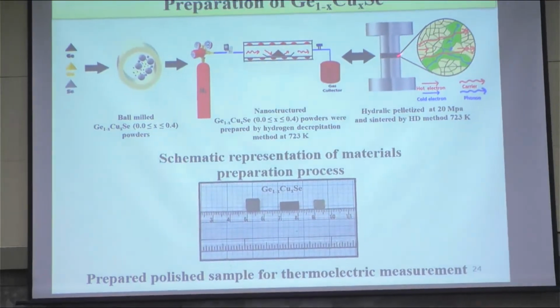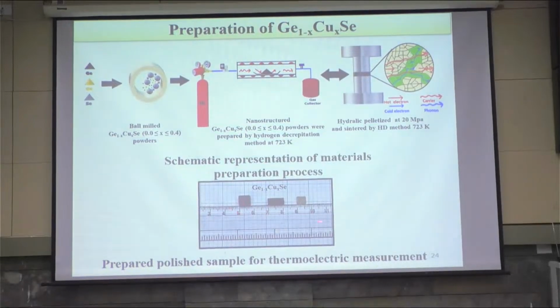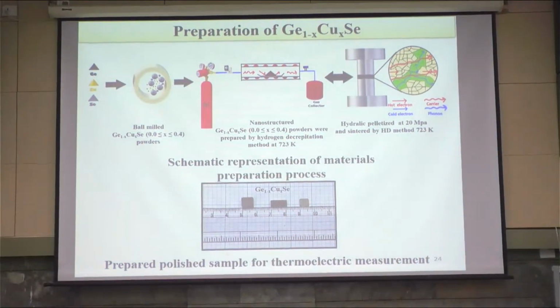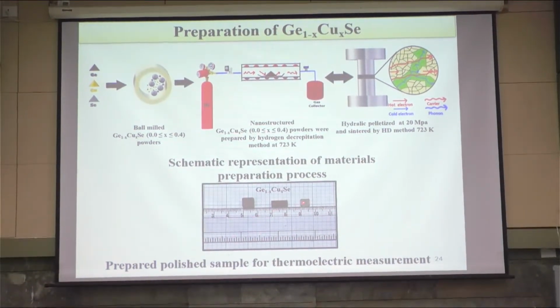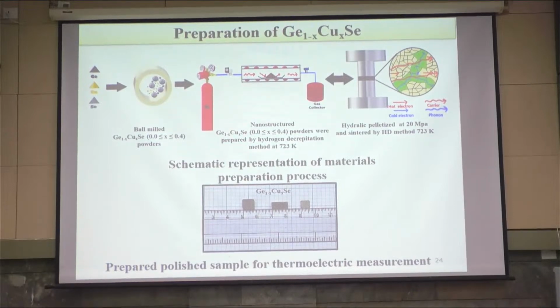And there we prepared the sample with this hydrogen decrepitation method, with different copper content, and these are all the synthesized samples after the hydrogen decrepitation, and then pelletized into these 3D nanostructured materials. And these pellets were used to measure all these transport characteristics.